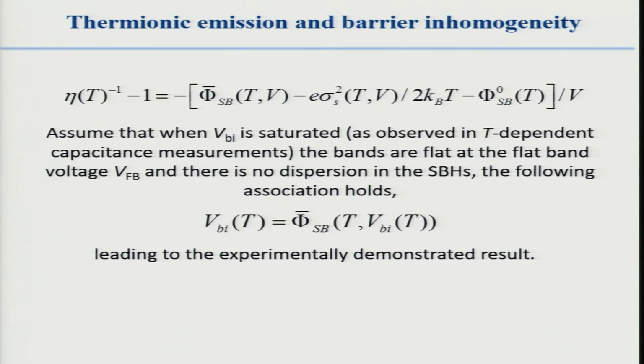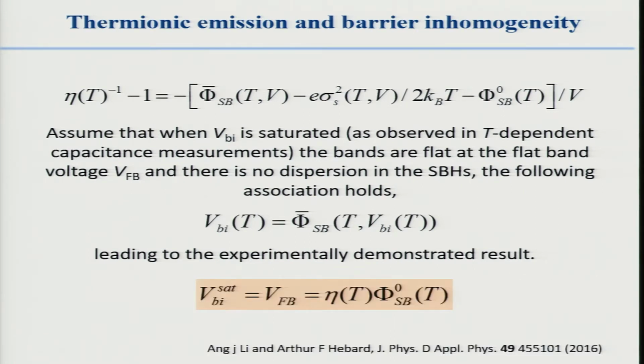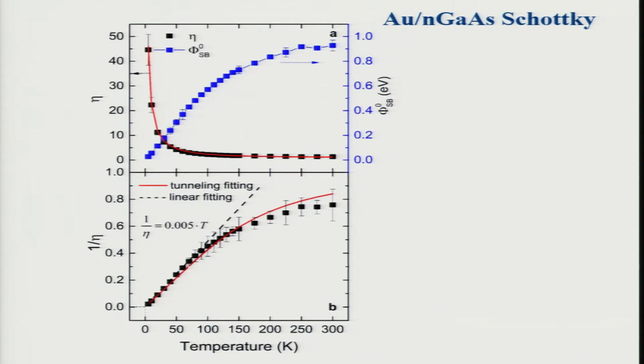Essentially, your V_BI, your built-in potential measurement, becomes a measurement of the average flat band voltage, which can be a function of temperature. And there's very little temperature dependence at low temperature. So this is an experimentally demonstrated result that our saturated V_BI is a product of the temperature dependence of the ideality and the zero voltage barrier height. Essentially, one has a linear temperature dependence, and this has an inverse temperature linear dependence. They cancel out, and I'll show you that. That was a surprise in this experiment.